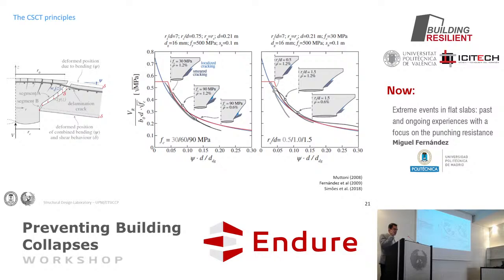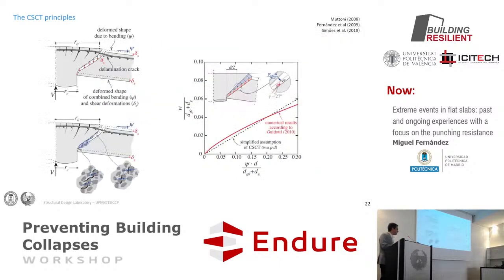So how do we simplify all this into something that we can use in a practical manner? And this idea was an original work by Professor Muttoni. By the way, that idea of how it could be calculated: these two parameter kinematical model, in fact, these two parameters are related, and this is a very good point. If you try to imagine that you have a crack, for instance, in an aggregate, if your crack opens little, then you need little penetration to have contact again. If your crack opens a lot, then you need lots of penetration to have contact again. So both are related. So the larger the psi, the larger the delta.